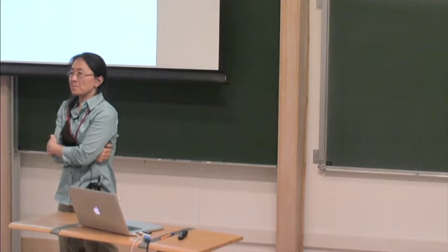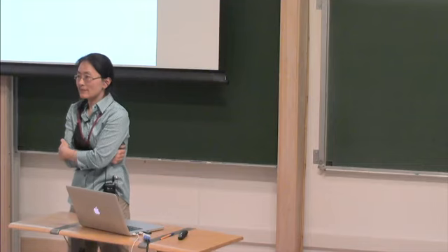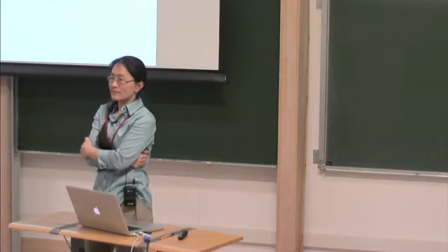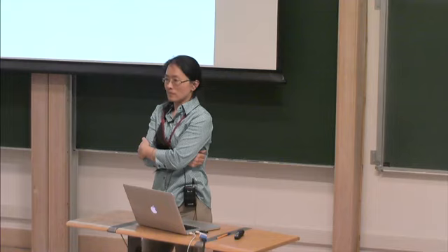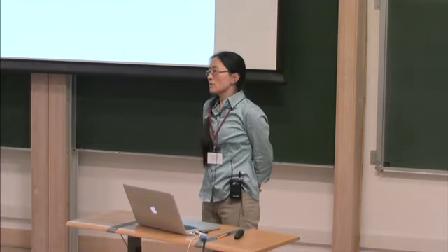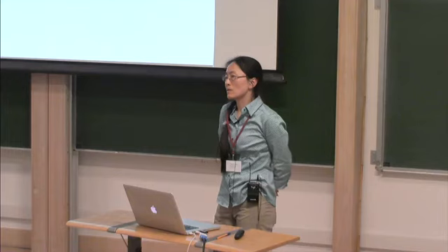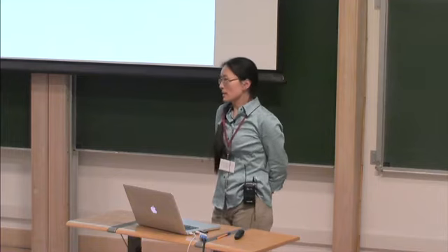So you mentioned that you are in the olivine OPX system. You are growing them from oxides. Do you see any oxides that are left over and unreacted? No. It's always 100% reactant. Okay. Because I was wondering if some of these issues you're seeing at very low melt fraction cases, or some of the differences that you're not seeing, could be attributed to oxides. We didn't see any of that.